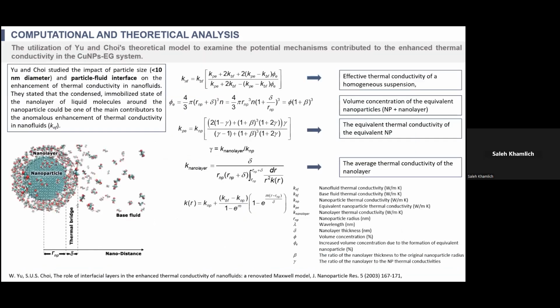So I'm not going to take long because of the time. We use other kinds of calculations. What I'm showing you here is the Yu and Choi theoretical model. These scientists use what we call the Maxwell model. They modify it by using some calculations based on what we call a layered structure around the nanoparticles. They stated that these molecules are adsorbed or approach the particles and create a layered structure. They call it a layered structure, which can contribute to enhancing thermal conductivity through this equation.